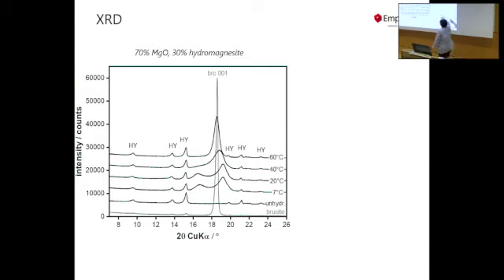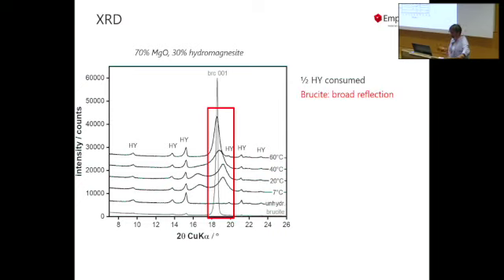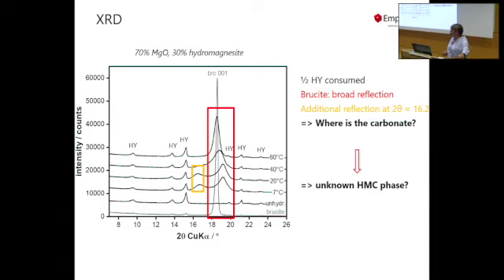If we look down here, I know I will be finished in 5 minutes. We see the brucite, and if we have the hydromagnesite mix, we still see a peak at a similar position as the brucite, but it's much more broad. So it must be something less ordered. We didn't find any new phases. We've seen half of our initially added hydromagnesite was consumed. The broad reflection I already mentioned. We could see some additional reflections, but we didn't see any really new phase. So we didn't really know what to think.